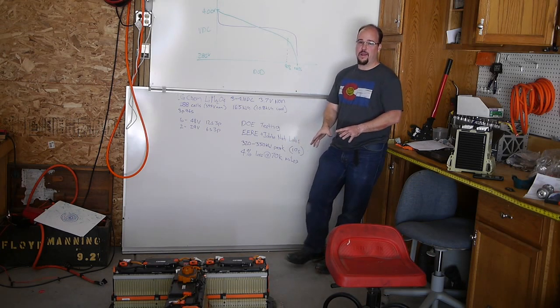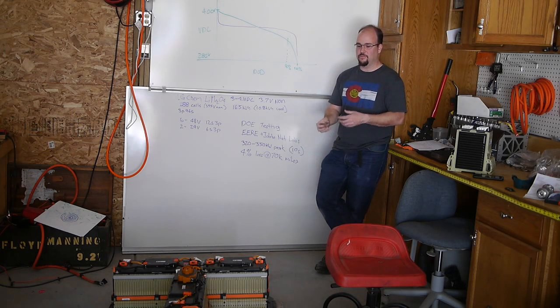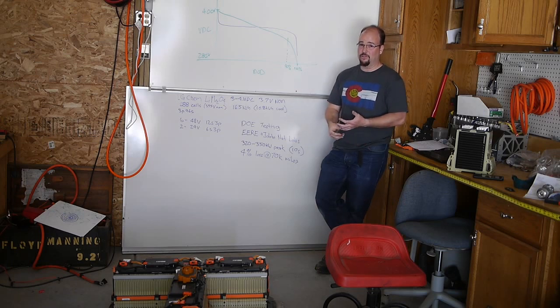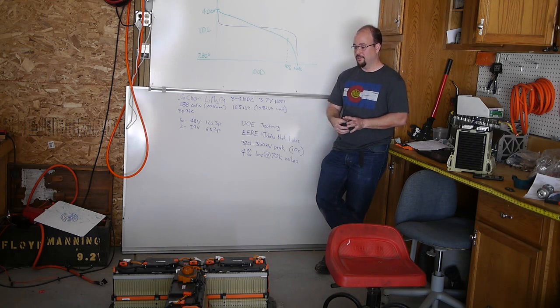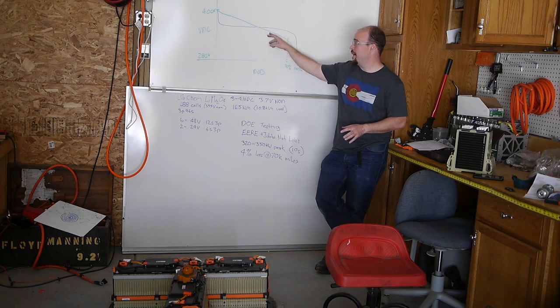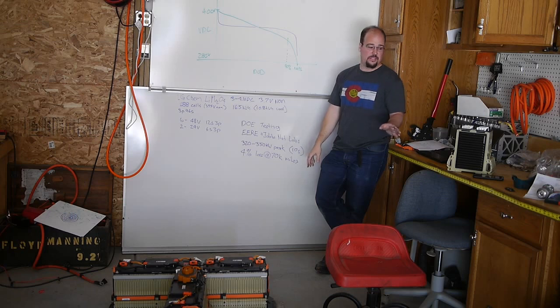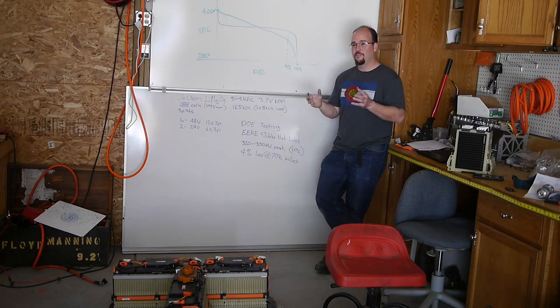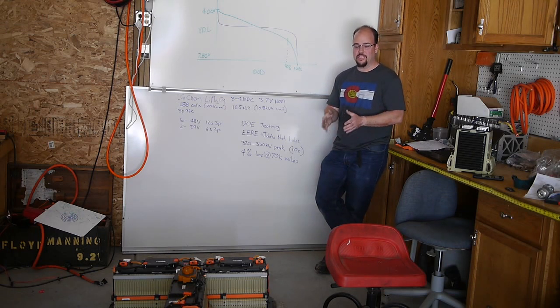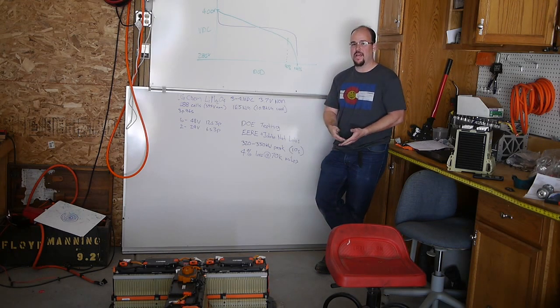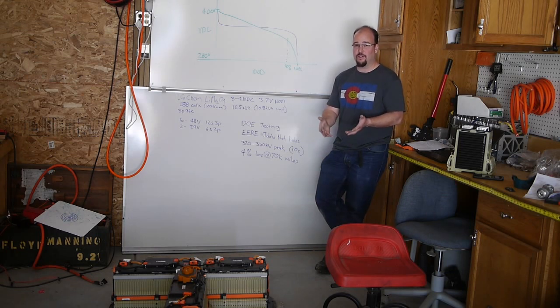Now, these are used packs, modules. They have had a BMS on them. The ones I've gotten are all less than 20,000 miles. That BMS's job is to balance all of the cells. But that balancing, it balances voltage. But not balancing voltage at rest, it's also doing it in state of charge. I've gone through some of the modules, and as accurately as my voltmeter can read, the cells that I have checked have been the same for the same pack. Meaning that they should have roughly the same state of charge.